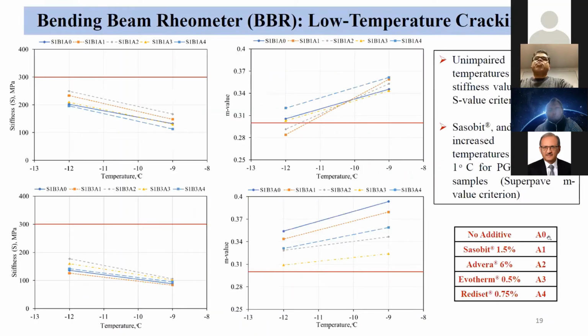Next, from the bending beam rheometer test, we could not find a significant or detrimental influence on low performance grade, especially from the S value, the stiffness value. It made the binders even softer, all of them. But in one case, Sasobit at 1.5%, the M value was on the borderline. It was even lower than